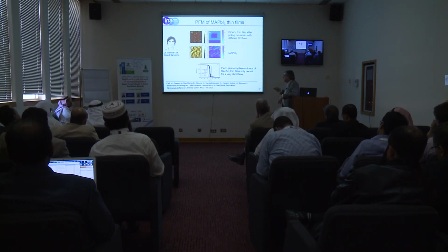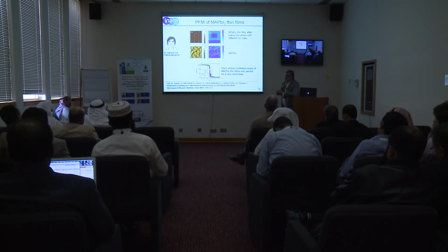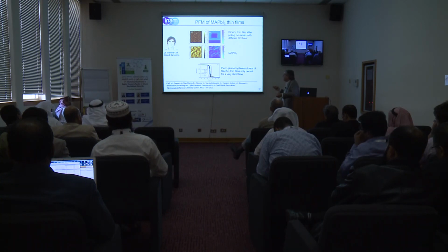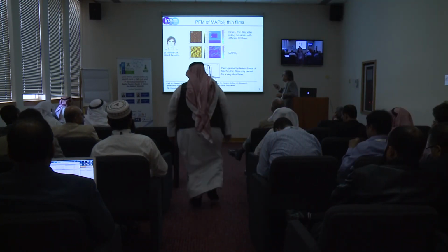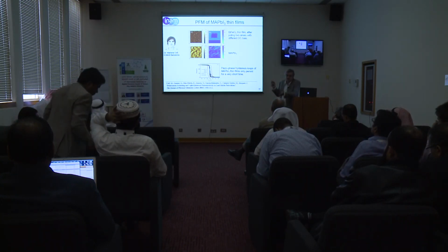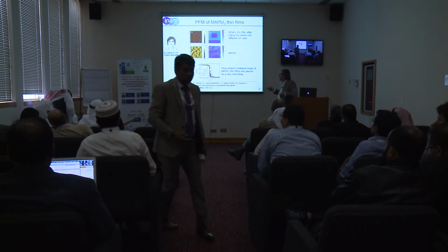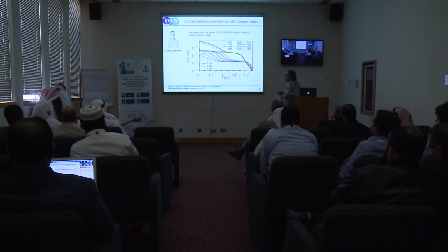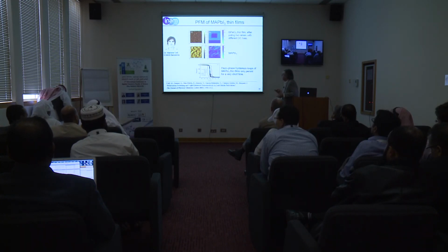So there is some dielectric polarization in the lead iodide perovskite, but it goes away very fast, so that we cannot induce permanent polarization. In bismuth iron oxide, you can polarize it, and this will stay for several days, polarized like that, okay? But in the perovskite, it will rapidly move away. So it seems we don't have a ferroelectric property.